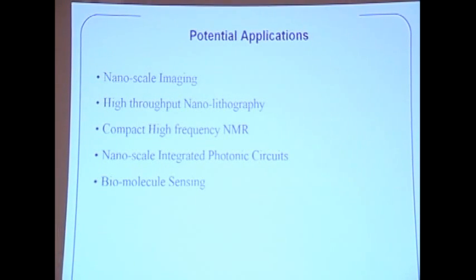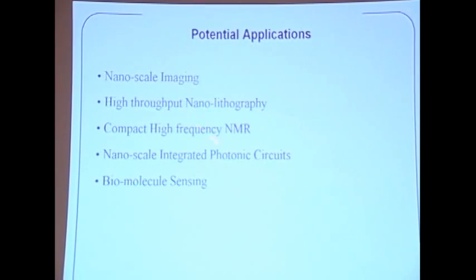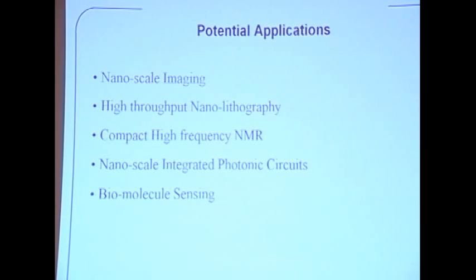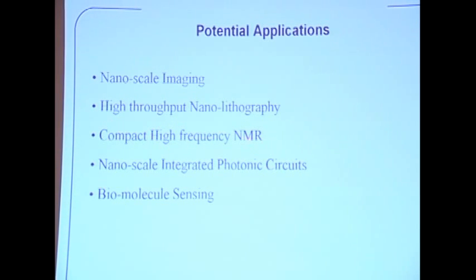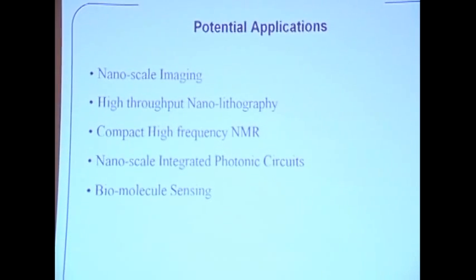Now, nanoscale imaging, if you can build this so-called super lens, high throughput nanolithography, by the same token, imaging and lithography are reversed processes. Also, many of you are probably familiar with medical imaging using magnetic resonance. One of the bottlenecks for current magnetic imaging is that the resolution is about sub-millimeter size. So if the doctor wants to know from MRI how big a tumor is, that is the resolution limit. If you want an even smaller resolution with magnetic imaging, you have to tune up the frequency of the oscillating magnets. And that has a bottleneck limit, because magnetic frequencies are limited by natural magnetic materials. If you can push up the magnetic response at very high frequency, and flip these dipoles at optical frequency, essentially that's a possibility to increase the magnetic imaging resolution.